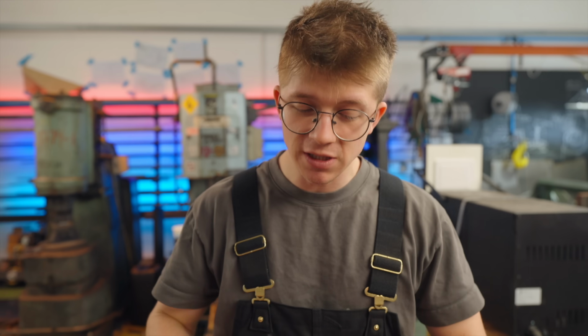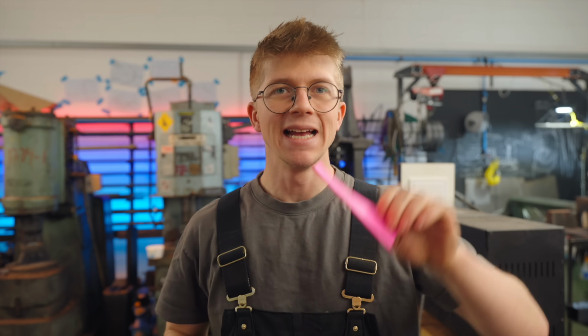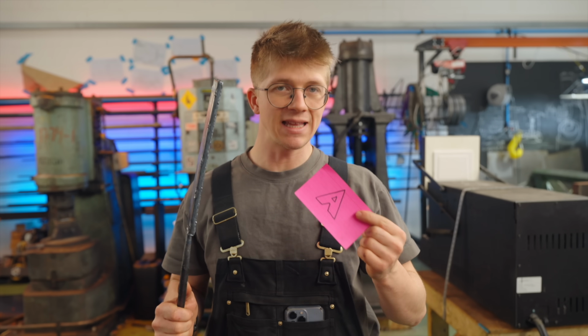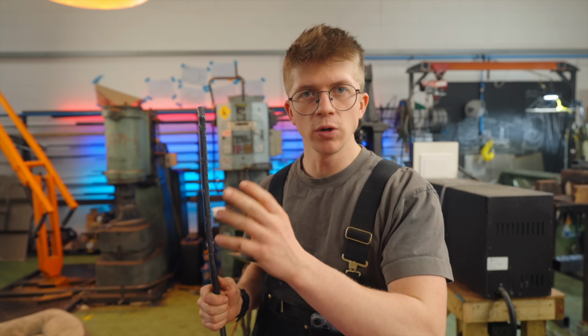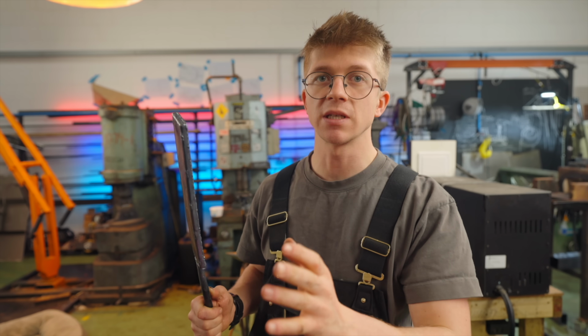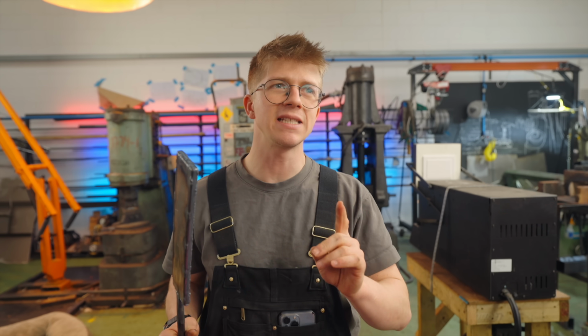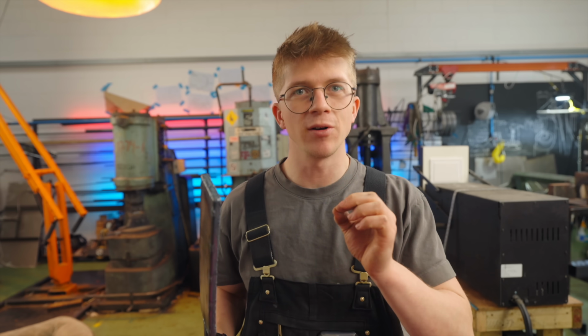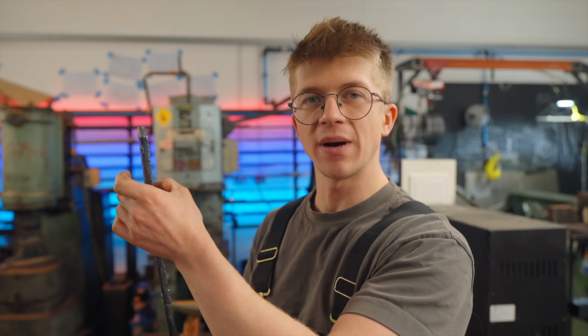And what I hypothesize will happen with billet A is we're not going to get the hardness that we ideally would want out of a blade from our steel core. Now, why do we think that might be? You guys made some amazing suggestions in the comments of that last video. In summary, remember that in order to harden steel, you need to heat it up to its hardening temperature and then quench it, cooling it as fast as possible, or at least cooling it at the appropriate rate that it requires for hardening. Well, our steel core is jacketed by titanium.